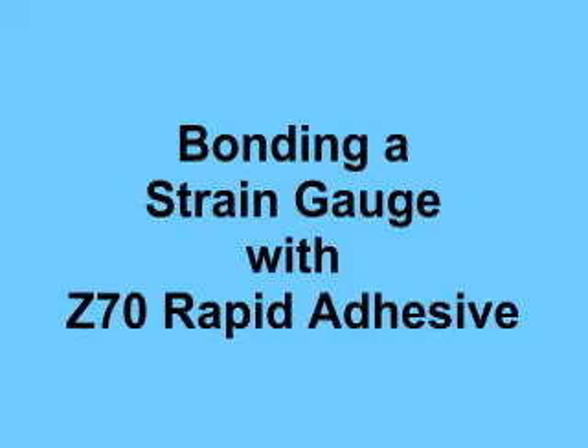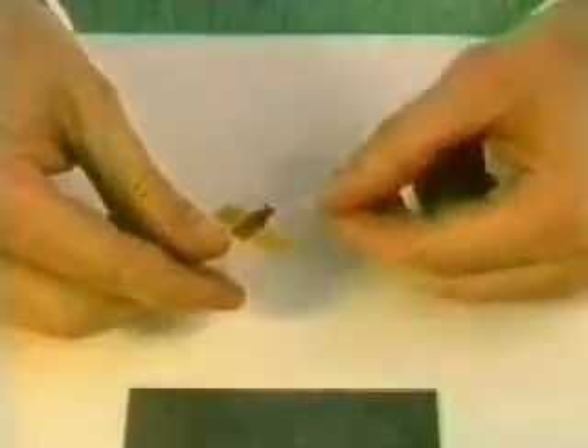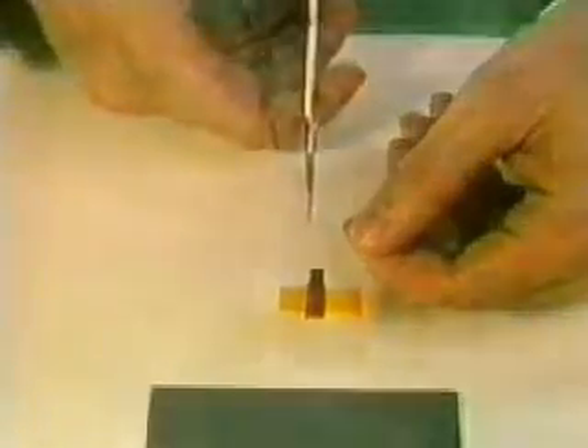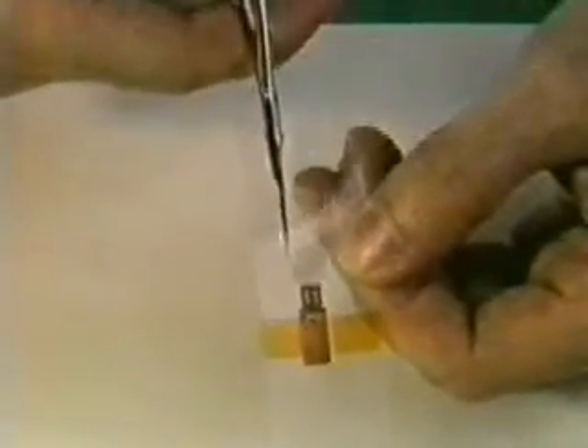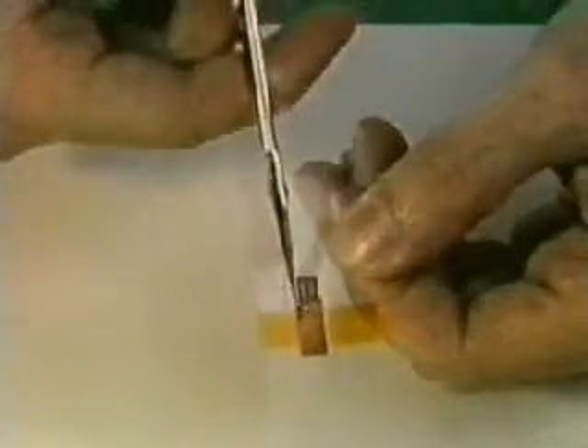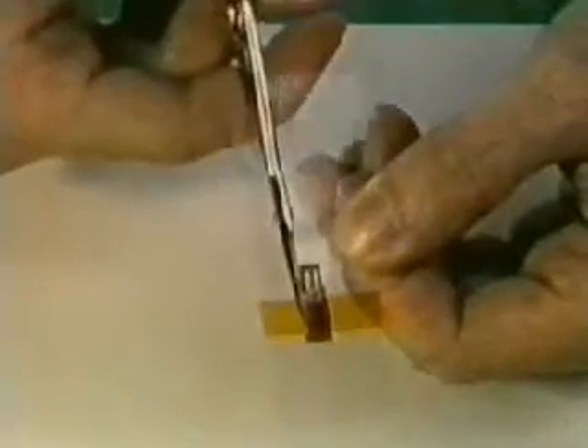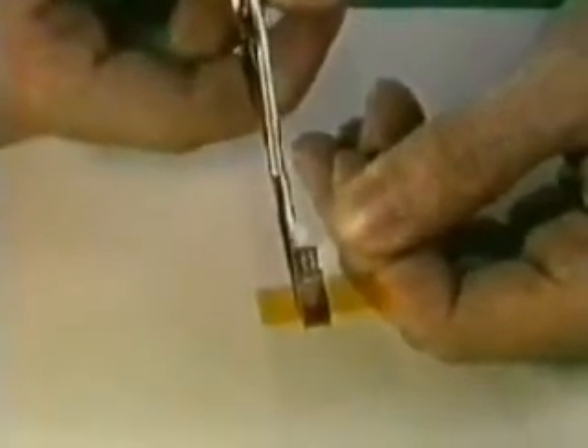Bonding a strain gauge with Z70 rapid adhesive. The mounting of the strain gauge should be carried out immediately after cleaning. The prepared strain gauge is taken out of its packing. If necessary, the adhesive strip is cut off with a pair of scissors along the longitudinal side of the strain gauge so that it only remains attached on one side. The strain gauge is then pulled off the film with a pair of tweezers. The tweezers should only grip the adhesive strip, never the strain gauge itself. Important: do not pull the strain gauge off towards the back.